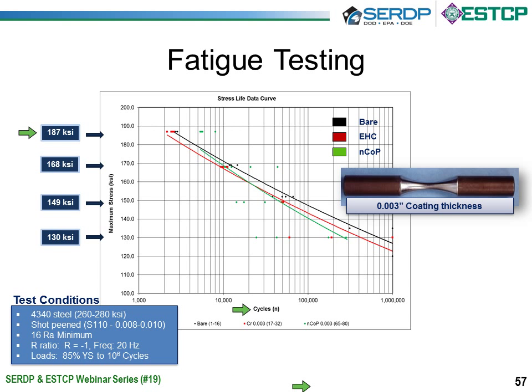For this particular example, what we're illustrating is 0.003 of an inch of coating thickness in both hard chrome and the cobalt phosphorus electroplate, and then comparing that to bare metal. This was high strength steel 4340, shot peened, and the testing parameters are also highlighted in the blue box at the lower portion of the screen.